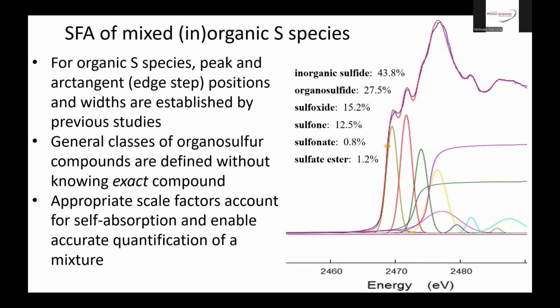And for organic sulfur species, the feature characteristics are pretty well established from previous measurements. So we can use that. And these apply to general organic sulfur compounds, general classes of them, rather than specific compounds. So there may be 500 different chemical compounds in there, but you can classify them into organic sulfide, sulfoxide, sulfone, sulfonate, and sulfate ester species. And each of those species will have very characteristic peak positions and characteristics.